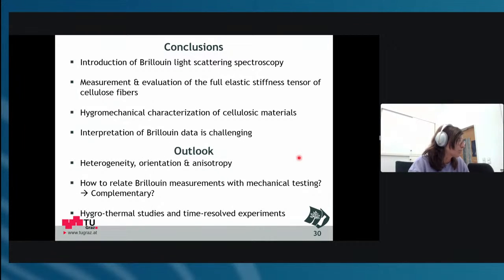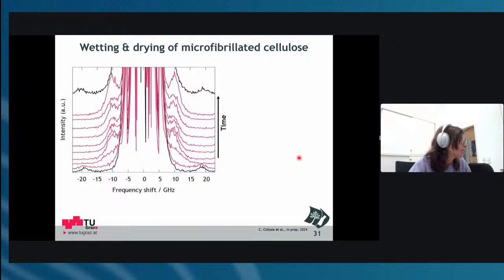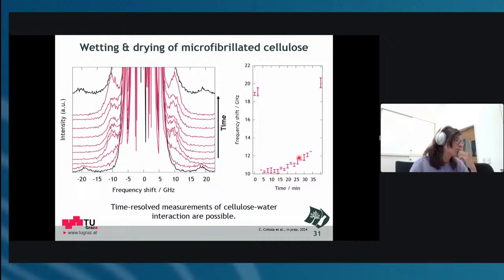As an outlook, I would be very interested to continue with anisotropy and now slowly introduce hygro and thermal measurements and also time resolution. The question is how to relate with mechanical testing. That's maybe a bit of a teaser. It's also working to really do time resolved measurements. We could look at drying, at least of cellulose material, over time, and we've had 2 minutes change in between.